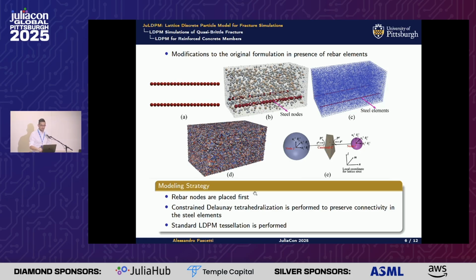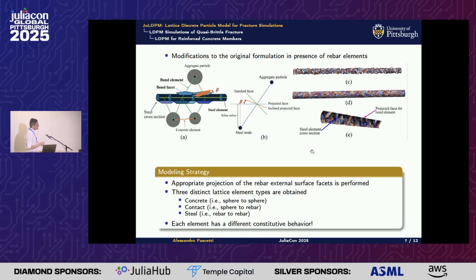Still, we perform the standard LDPM tessellation, but now this is a little bit more complicated. And so what happens is that now we have the coexistence of 3 different types of lattice elements. If you look around each of the rebar elements, you have particle nodes, which represent the concrete, that interact with your rebar nodes, obviously. And so you have 3 types of elements. You have the concrete element, which is concrete to concrete node. Then you have some form of contact element, or bond-slip element, as it's sometimes called in numerical modeling. Whenever a concrete node is connected to the rebar, such as one of these 2 inclined members, that's of course a contact lattice element, and then you have all the steel elements, which are of course rebar to rebar.